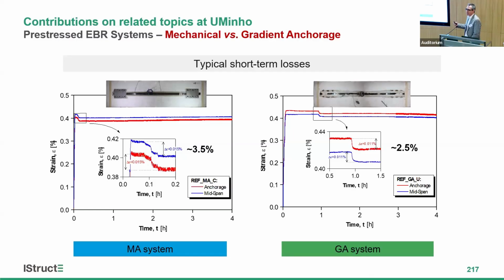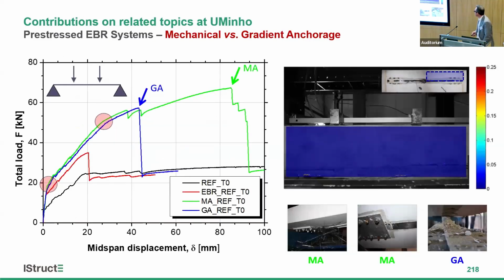Unfortunately, I don't have time to explain, but this is when we fix the hydraulic jack, and the loss is around 3.5% of the strain variation. And while in the case of the gradient anchorage, you can see here we have always the same loss, but here, in the first release of the force, it is around 2.5%.